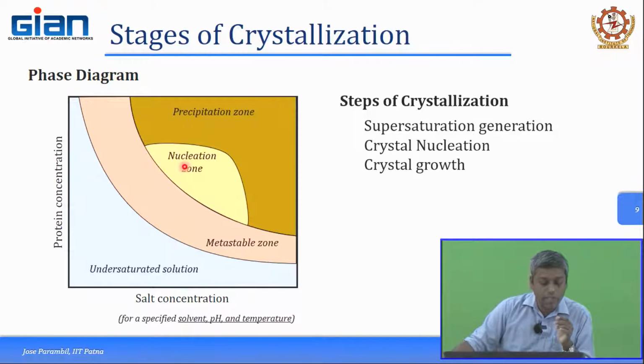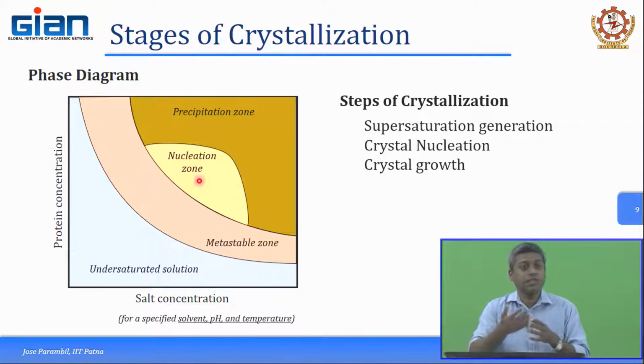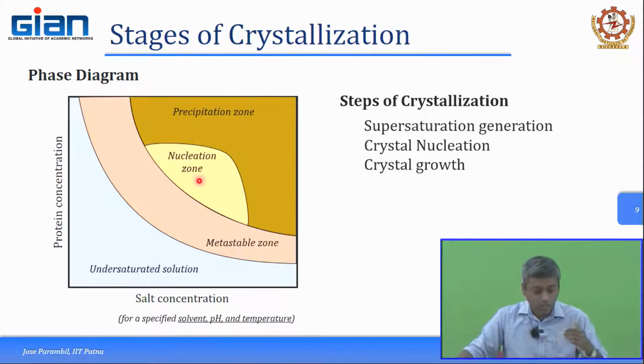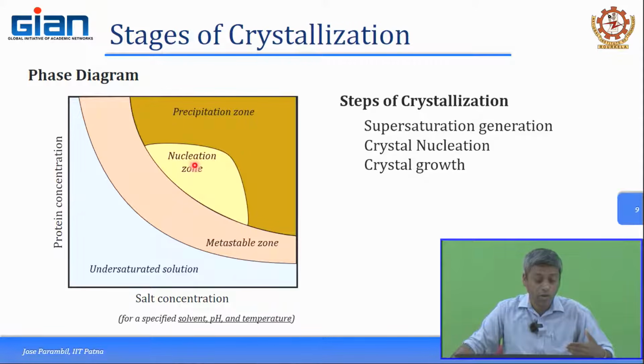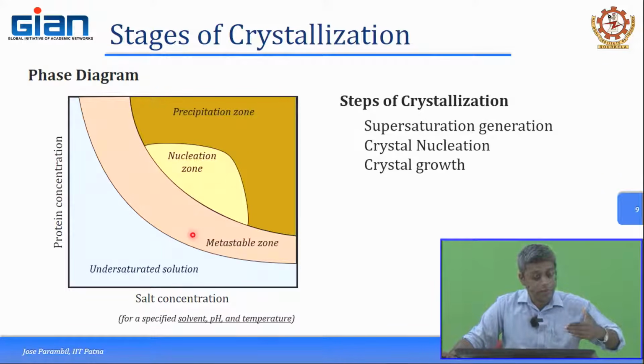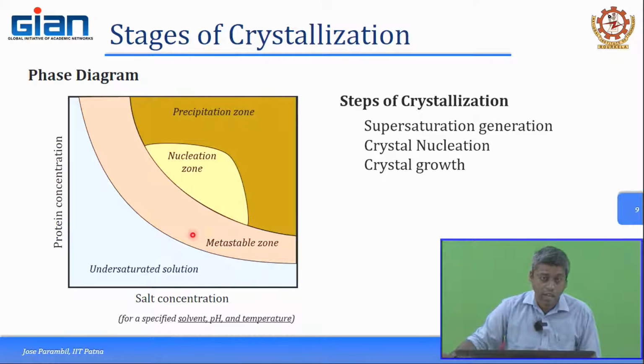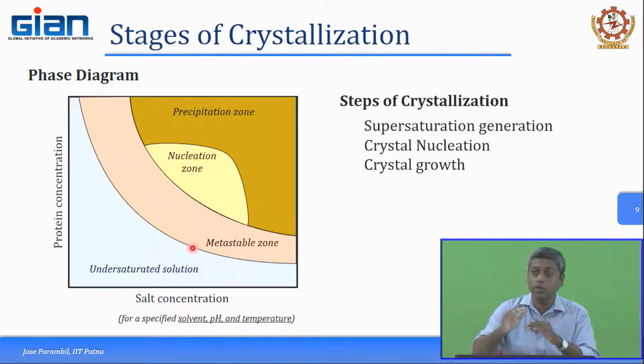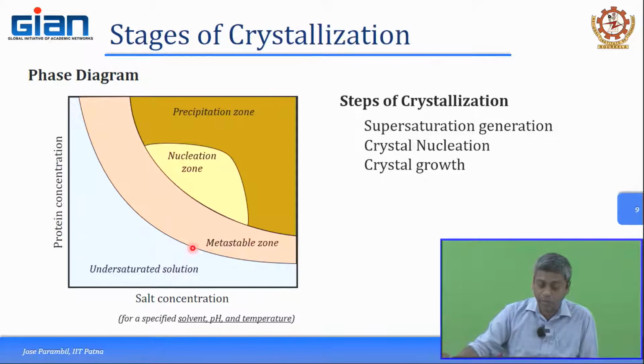So, if you are within this zone, nucleation can occur, and as the nucleation occurs, it starts consuming the proteins. So, the protein concentration would fall, which means that it might come down and move along this line vertically, from the nucleation zone into the metastable zone, and once it reaches the solubility line, it stabilizes. Once it reaches the solubility line, the solid form is in equilibrium with the liquid. So, then no further changes occur and it stabilizes at that point.